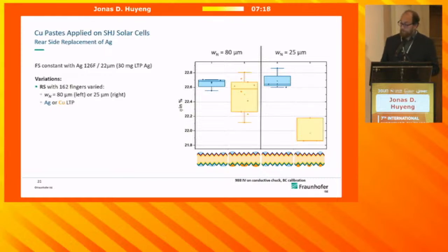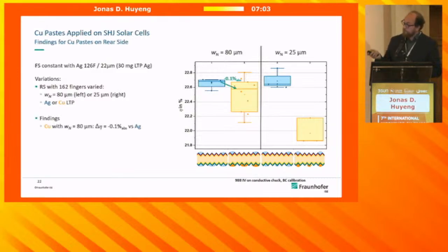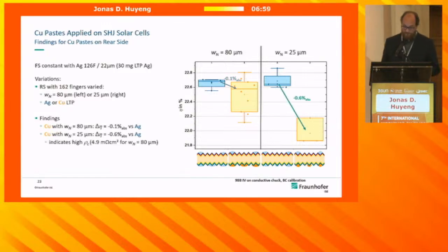But then if you look at the copper material that we had in this study, you can see that there's a challenge for the material to pass through the 25 micron opening. So again, there's a challenge in the printability that needs to be addressed. And then in terms of efficiency drops, we can see there's a slight efficiency drop for the wider grid lines and a larger one for the smaller grid lines. It's not only the line resistance, we've also noticed that there's an increased contact resistivity for this material, so there needs to be some more work put into this.